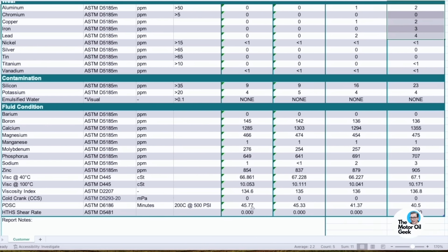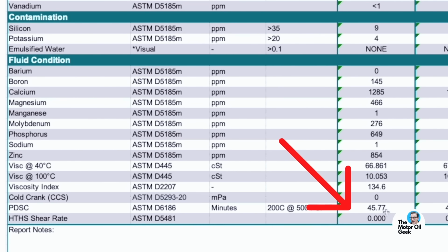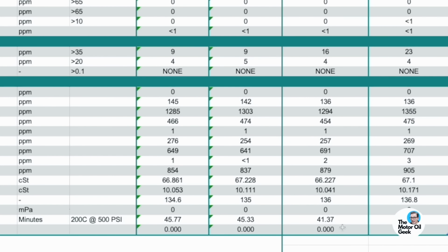That PDSC number, that oxidation stability, out of the bottle, 0 hour sample is right at 45 minutes. And then after running it for an hour, it lost about 3 to 4 minutes, and then it lost another minute after the second hour of testing. So we went from basically 45 minutes down to 40 minutes. So we had about a 10% decrease in the life of the oil just on 2 hours of that high temperature running with the conventional oil.